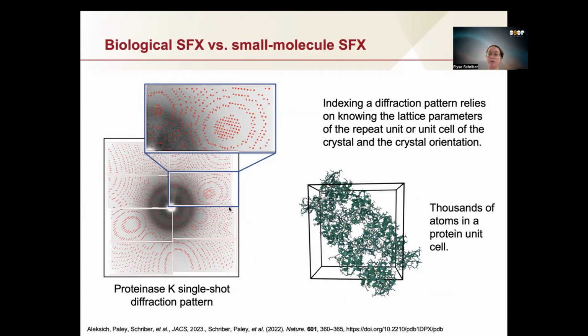And what that allows us to do is index this by using the periodicity of the already present spots. And it also relies on knowing lattice parameters of the repeat unit. And with biological molecules, it's a lot easier to attain. This allows us to extract the crystal orientation that is lost during an SFX experiment.